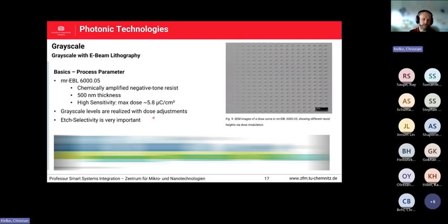And what is very important, what I forgot to mention so far, is shown here on the schematic. For example, for this application, we want to have pyramid structures or frustum structures, and to etch them in 500 nanometer silicon dioxide, meaning, first of all, you have to realize 500 nanometer resist and deal with really nice structures in the photoresist layer itself. What you can see here in the dose modulation is a very low dose going up to a very high dose, where you really see the structures coming up in height much better compared to the left side. And then you have the one in the photoresist layer.